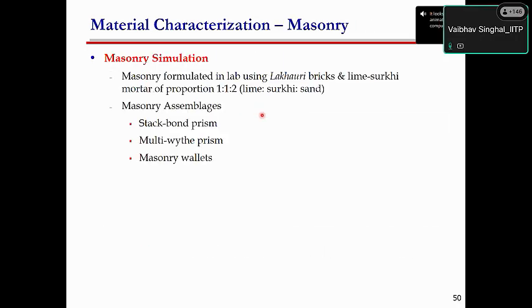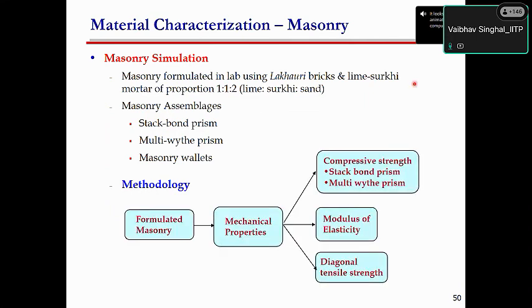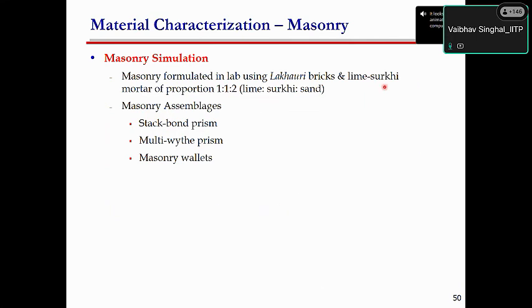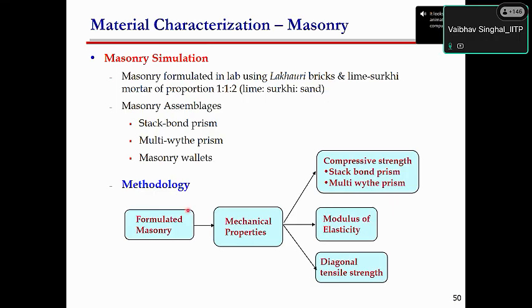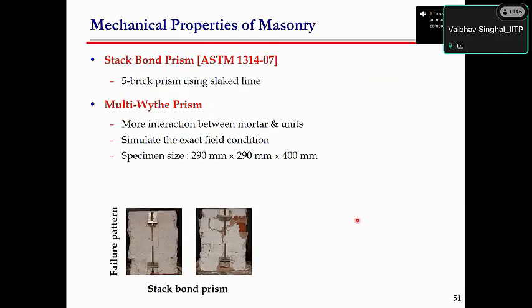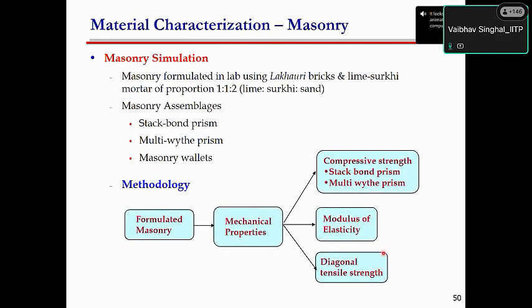Then using the properties of the bricks and the properties of the lime, we recreated the lime in the lab and developed some specimens. The first specimen is a stack bond prism, then the multi-wythe prism, and then the masonry wallets for finding out the tensile strength or shear strength. We formulated the masonry, finding out the mechanical properties using the stack bond prism and the multi-wythe prism, then the elastic modulus, and then the diagonal tensile strength.